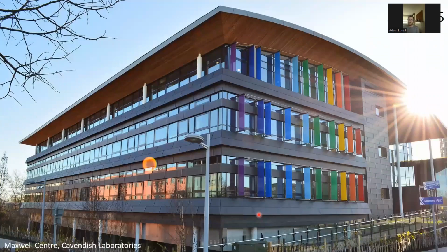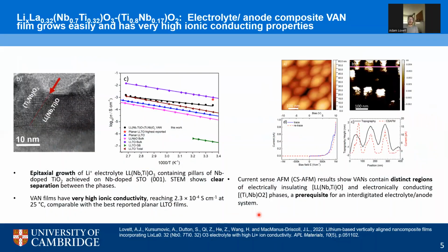So on to some results. In the top half of my poster, you'll find a segment on our recently published paper in APL Materials on this lithium lanthanum niobium titanium oxide electrolyte with niobium-doped titanium oxide anatase nanocolumns embedded in it. This is effectively an electrolyte-anode VAN system. From the TEM, we have really high crystallinity and clear phase separation between the 2 phases. The titanium oxide phase is clearly seen protruding the surface of a dense matrix film.